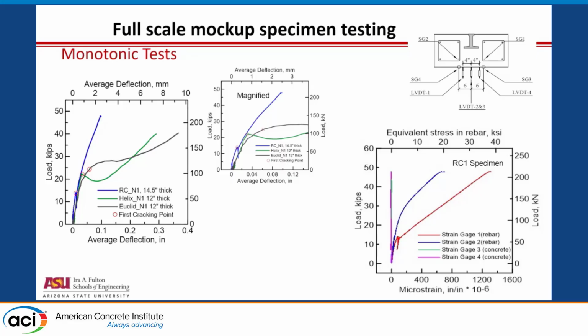Of course, what we can do is get a closer look and find out exactly when the system cracks. So the current design cracks, it's designed well because you have a factor of safety of about 1.5 on it. It cracks at about 13 to 14 kips, but then the fiber reinforced concrete goes up to more than twice that because the fibers suppress the localization. The fibers stop the cracks from forming, especially when the size of the sample is getting large.